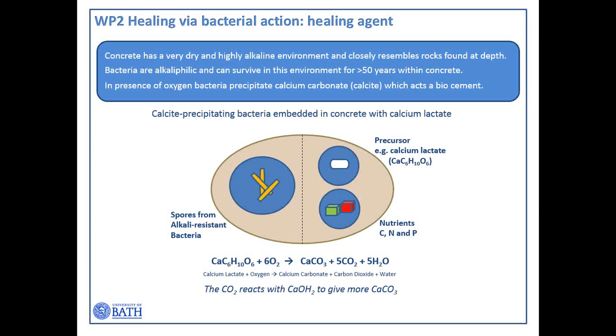So they're introducing these bacteria. The aim is to introduce these bacteria into concrete along with a precursor and nutrients, and these can then lie dormant within the concrete matrix until cracking occurs, at which point, from a bacterial point of view, the environment becomes more desirable. And due to this, these spores then begin to germinate, and they feed off the nutrients and act as a catalyst for the production of calcite within the concrete, which then fills in cracks at a slightly larger scale from the microcapsules being developed by Cambridge University. So by combining these systems, we then have two different systems which can work to heal cracks of different sizes.